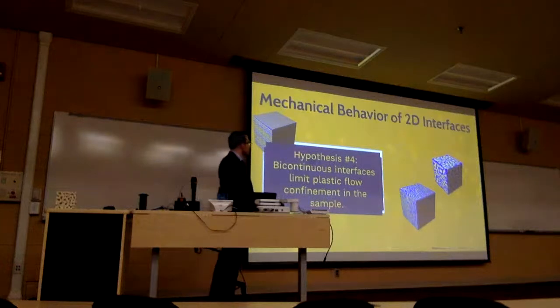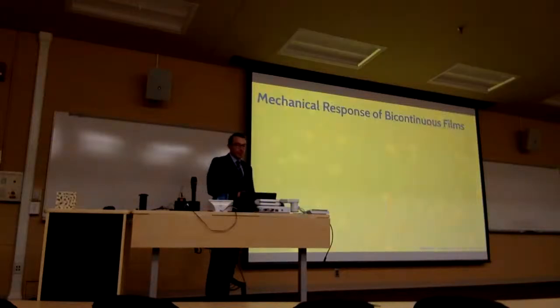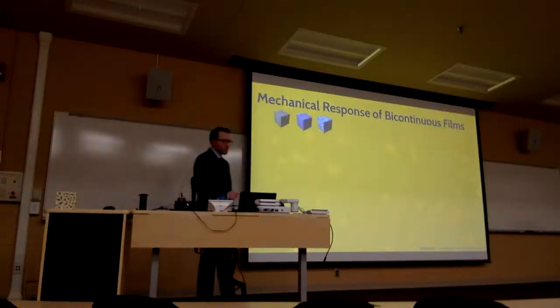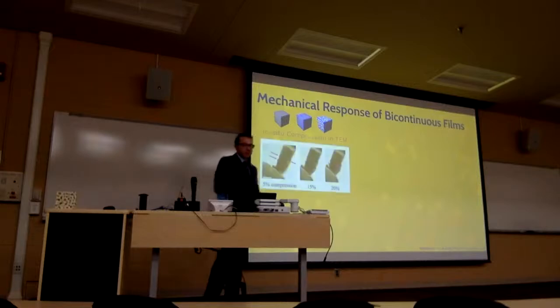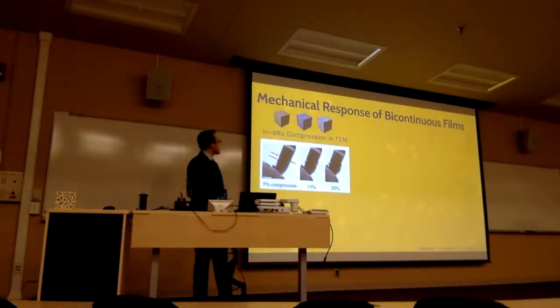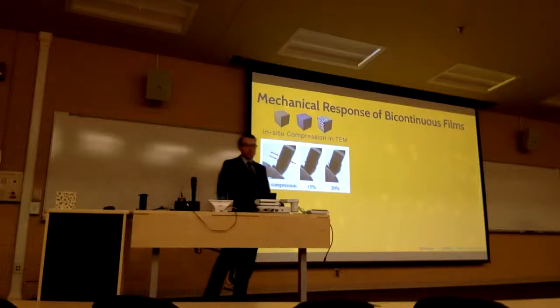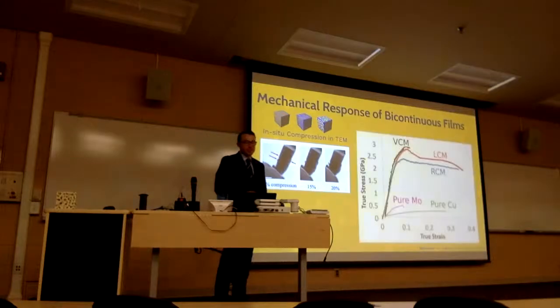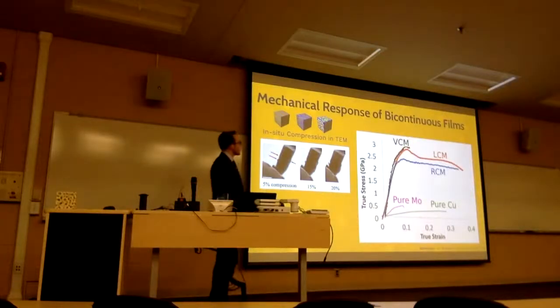Our hypothesis is that plastic flow is no longer confined in the sample, and the sample can be much more deformable. So my colleague Yushi Sui here at Michigan actually led a study where he compressed these 3 morphologies in a novel TEM experiment and gave us the resultant stress-strain curve for each of these morphologies. And you can see that labeled here.